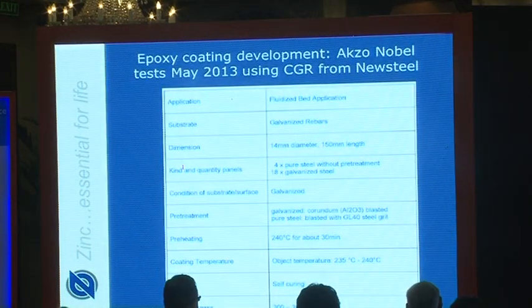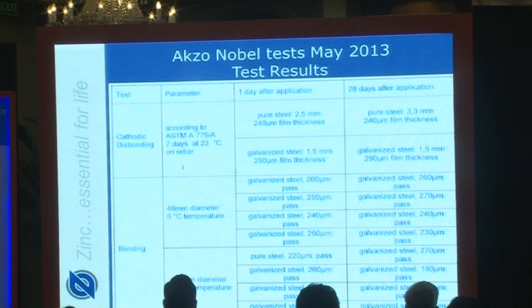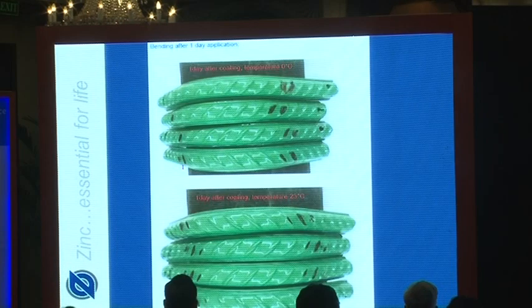And the other thing has been the development of the epoxy coating. We've had a very cooperative partner with Akzo Nobel. They've been able to come up with an epoxy coating process, and we show here some examples. I'll skip this because we're running out of time. If we bend after 1 day, we see on the top that's at 0 degrees C, so this is a low temperature. It's a challenge for the epoxy that we don't have any cracks on the bends.